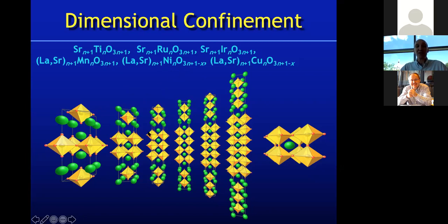Again, related to these structures, and you could think of taking oxygen out of the structures, again, a chemical trick at low temperature where you kinetically limit the structure and then suck oxygen out of the structure. Okay, and of course the cuprates, yes. So the high temperature superconductors, the lanthanum strontium cuprate, lanthanum barium cuprate, it's how this all started, are this structure over here on the left. You can think of YBCO as being the N equals two member with some oxygen vacancies in here. So the cuprate superconductors also are related to this, the Ruddlesden-Popper phases.